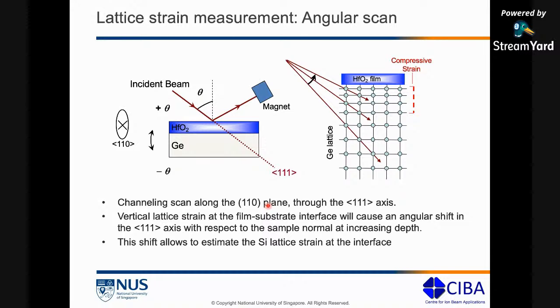Moving on to lattice strain measurement. Okay, this is one of the applications, like I said, for the ion channeling technique. Now, why is this important? Why is lattice strain so important? If you're familiar with semiconductors, or electronic materials, a lot of these electronic devices use some sort of an amorphous film, an oxide film, on a single crystal substrate. So we have silicon oxide on silicon, then we have hafnium oxide on silicon, and nowadays they are using hafnium oxide on germanium.